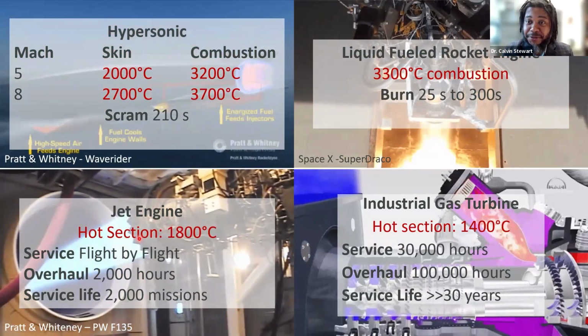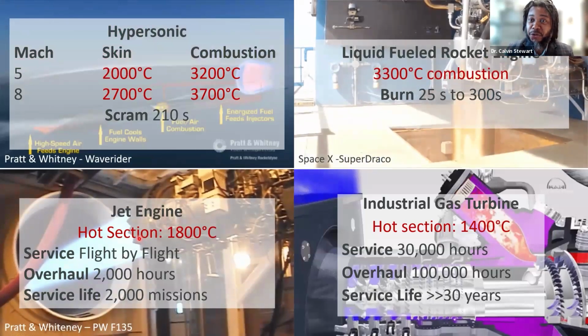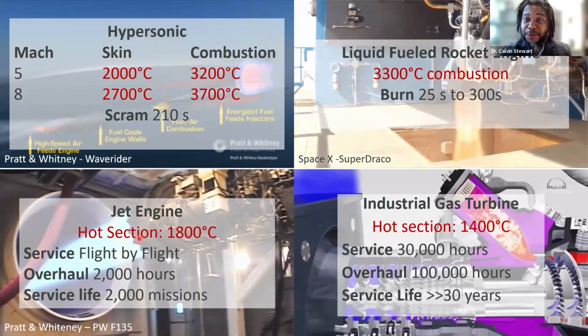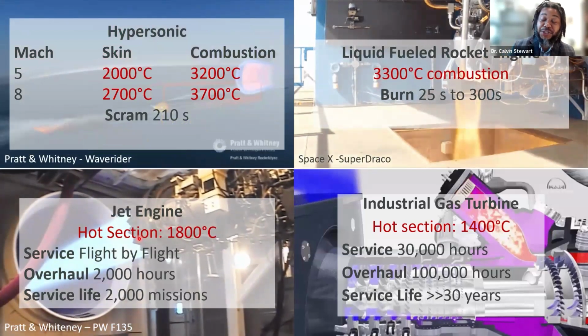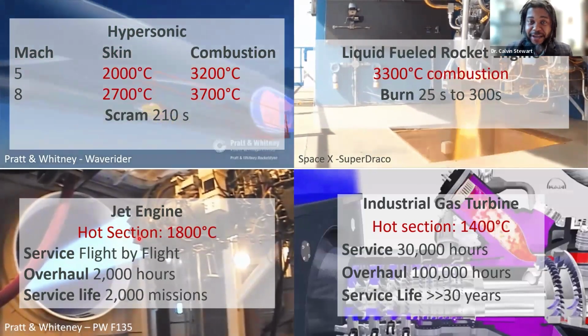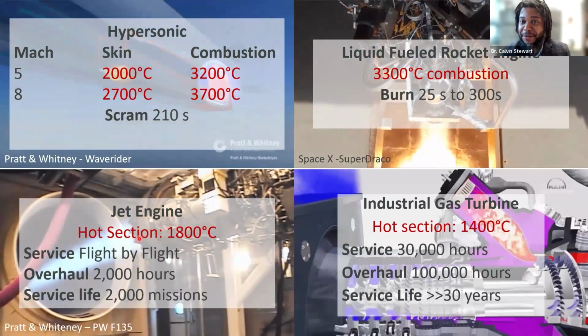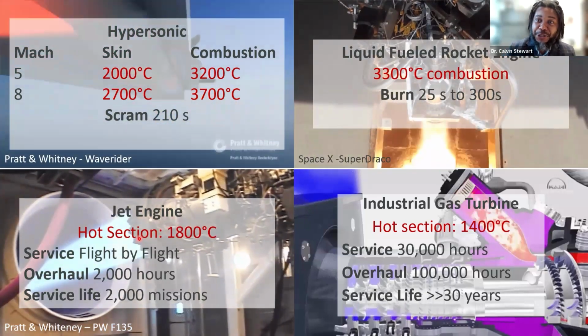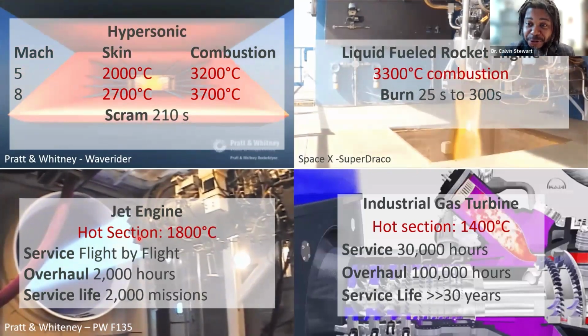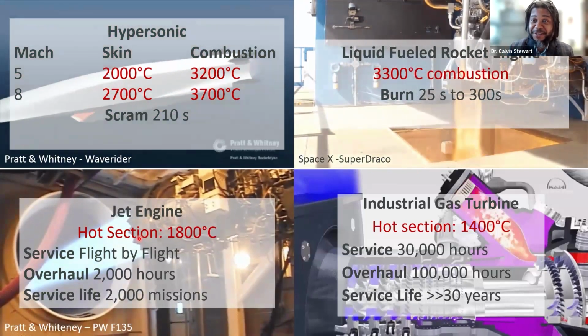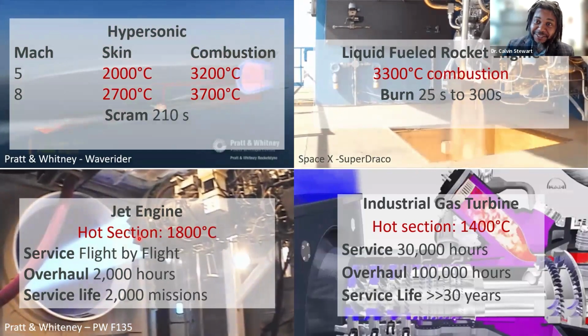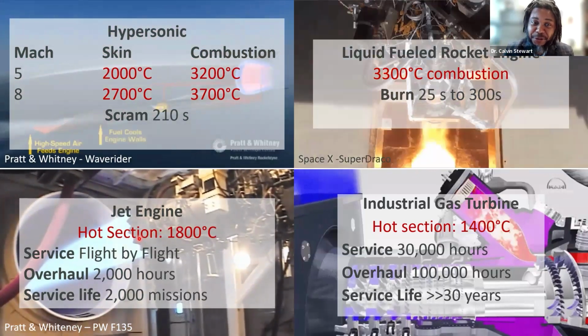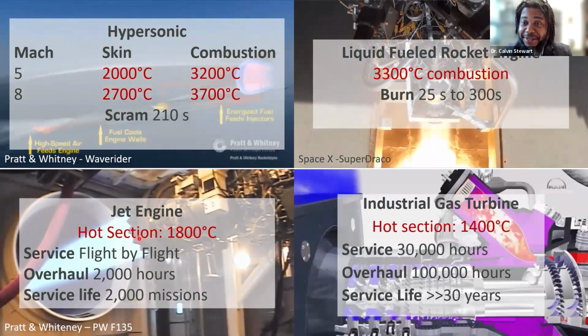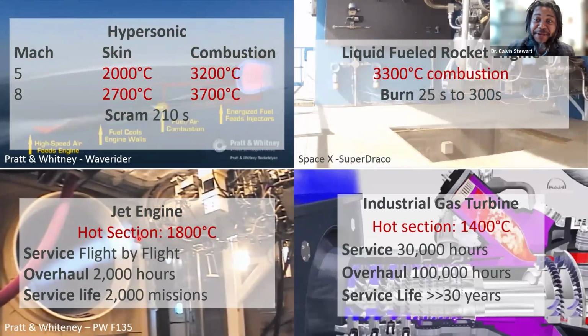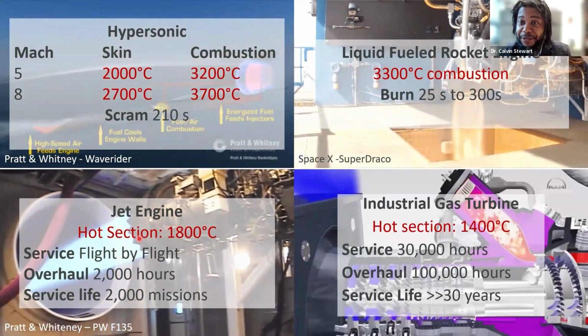their combustion nozzle and burning for about 8 minutes to get to orbit, and maybe flying multiple missions, to jet engines, to our fighter aircraft that are subject to flight dynamics and have turbine entry temperatures exceeding 1,800 degrees Celsius, or even the low temperature but still extreme industrial gas turbines, which are subject to 1,400 degrees Celsius and can be asked to survive and operate for up to 30 years or more.